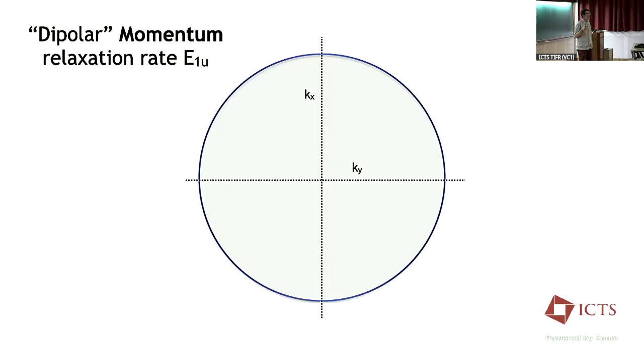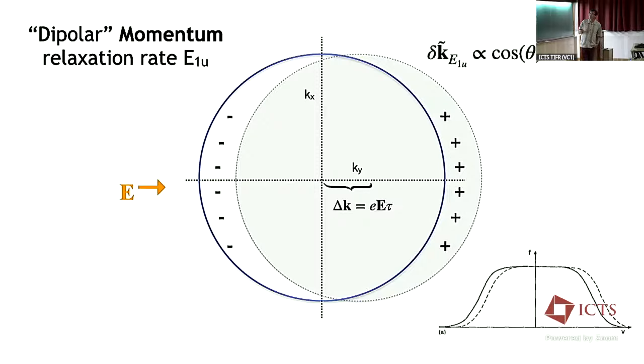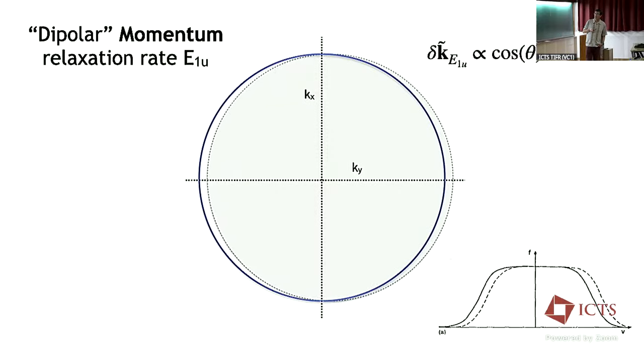So we could imagine taking this Fermi surface and perturbing it sideways. Some image like this appears in most people's first condensed matter physics class. Maybe this is how it's done in Kittel. And you think about perturbing the Fermi surface sideways, and you fill in those states and you deplete those states. And to use the language we're going to use later on, we'll consider this a p-wave deformation of the Fermi surface. This is a state of finite momentum, and a time domain optical conductivity experiment would be where we've displaced the Fermi surface sideways, and then we watch it relax in time, back to the state of zero momentum. And so really what is relaxing in this situation is momentum.